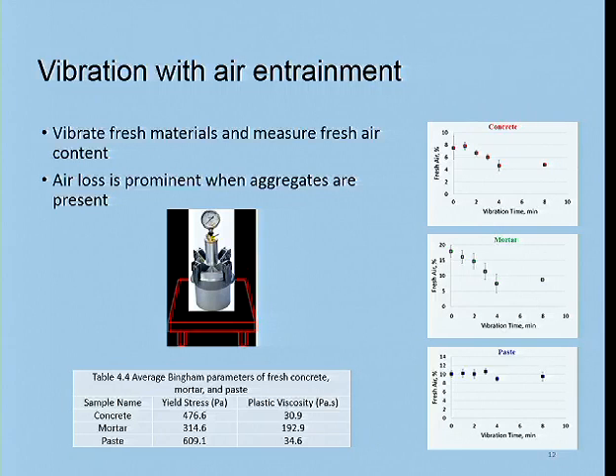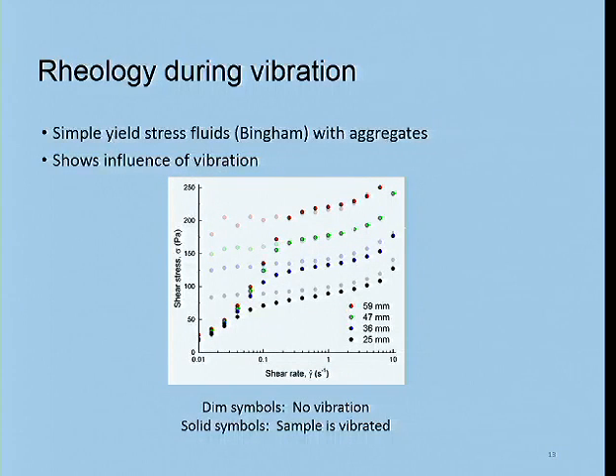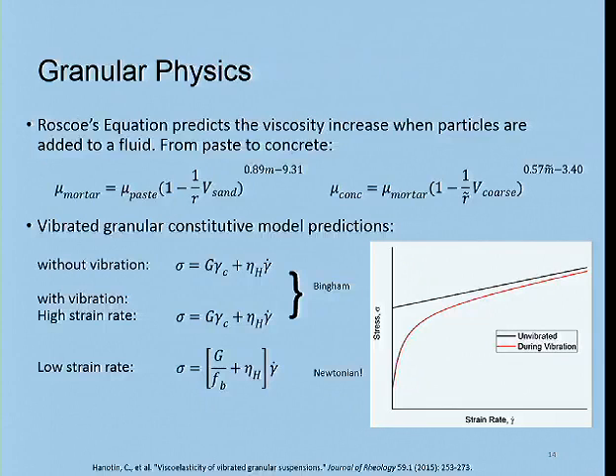Something about the presence of aggregate in concrete and mortar, and the lack of aggregate when we're working with paste, makes a big difference. And that leads us to think about the granularity of these materials. So this is another picture where we did some tests with a sweep of viscosity, or the behavior, with a rheometer, and we could do this with different size aggregates. The light dim symbols are when we don't have vibration, and when we turn on vibration, our sweep indicates we have this very different kind of drop in yield stress at the slow strain rates. So we know that the aggregates have a pretty important part to play in this problem.